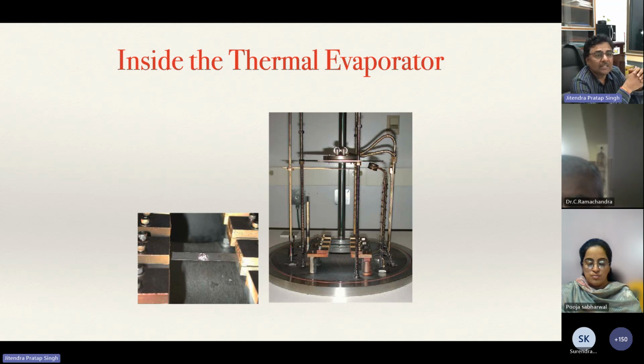Some materials, it depends on the material, because in some materials the surface diffusion is very high. Like gold, which has a very high diffusion rate, so it actually goes inside the material also. Both the surface diffusion and the bulk diffusion are very high. In thermal evaporation, the molecules land on the surface, but they also have momentum, a particular direction and some energy. So they have to thermalize, meaning their kinetic energy has to go down to zero. Then only they will stop.